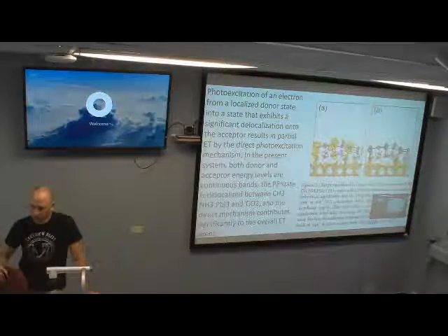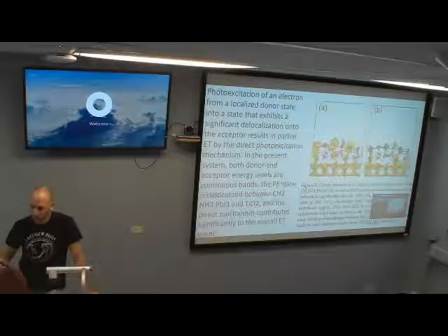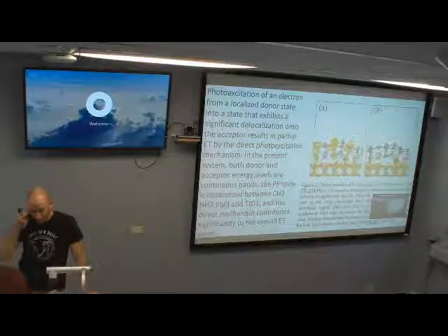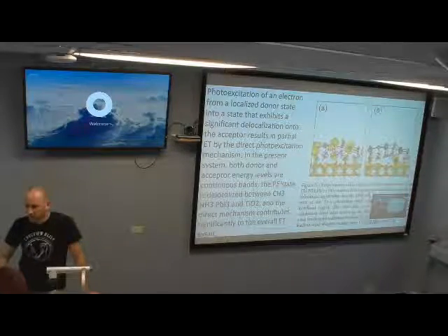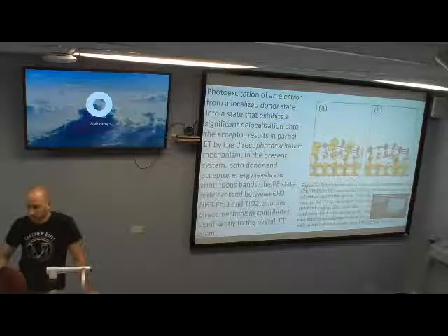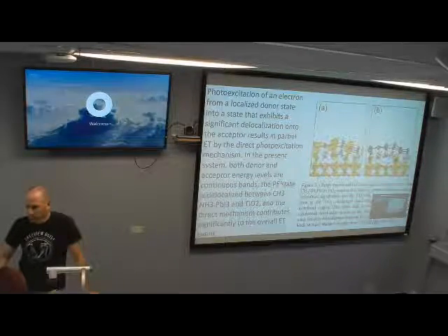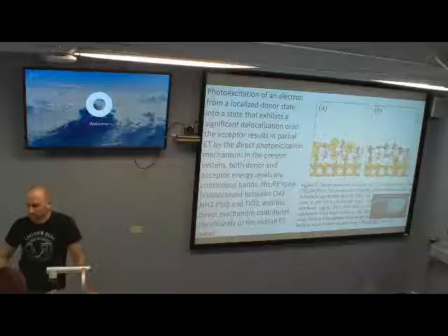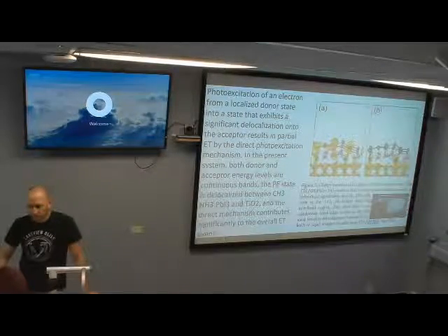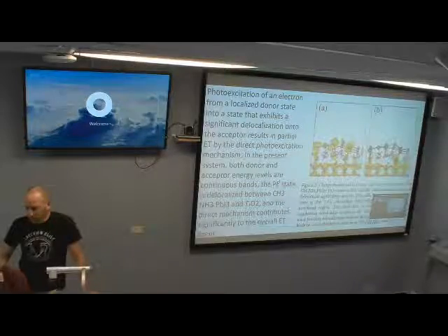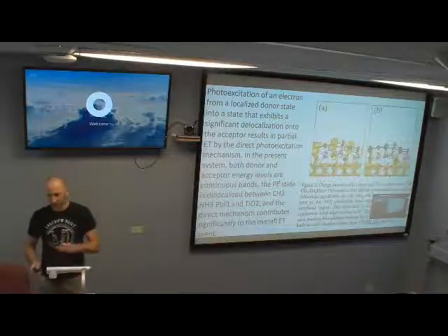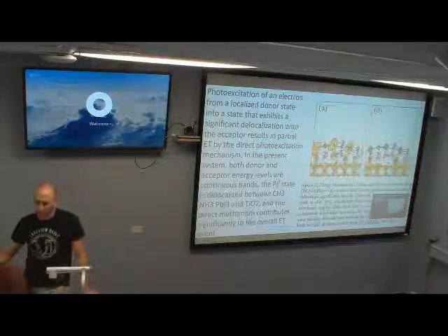Here, the periodicity of the box is selected to match titanium dioxide and perovskite, whereas your titanium dioxide is a cluster, a quantum dot. Therefore, it doesn't affect the size of the box and doesn't create any strain. It is one of the reasons to choose the geometry that you are pursuing, to avoid possible errors due to strain. The only strain I'm aware of is because of the interface itself, where titanium dioxide would push in or pull out the perovskite.